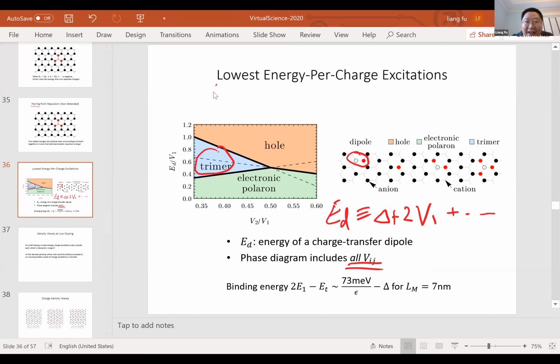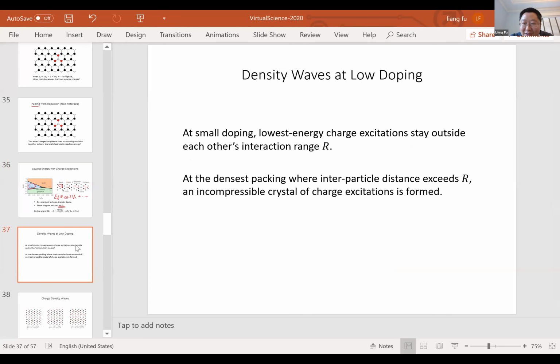So here we basically discussed energy excitations with the lowest energy per charge. This is still excitation at the filling one. But now let us consider finite doping, a small amount of doping, finite density but small. One would expect that when the doping is small, the ground state will be formed by these lowest energy charge excitations, and they want to avoid each other as much as they can. Let's suppose that the interaction, due to the screening by the metallic gates, has some finite range which we call R. At sufficiently small doping, these low energy charge excitations can stay away from each other's interaction range R.